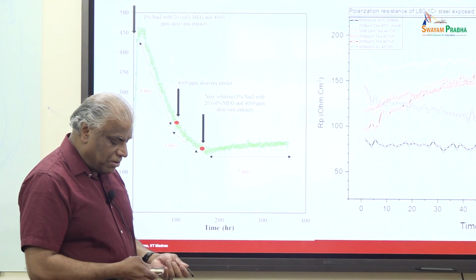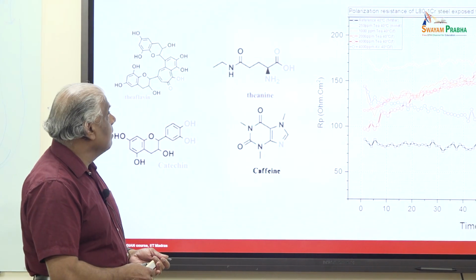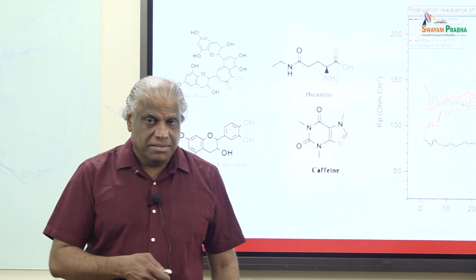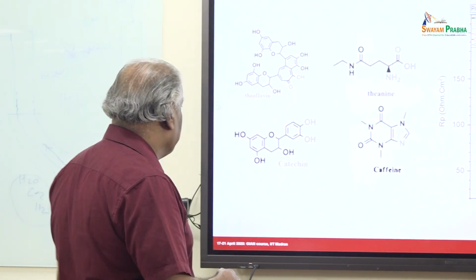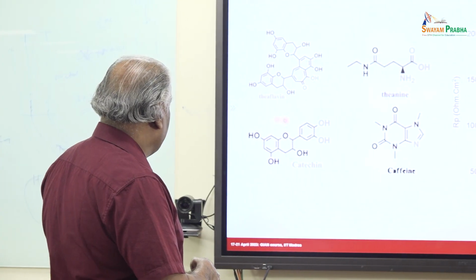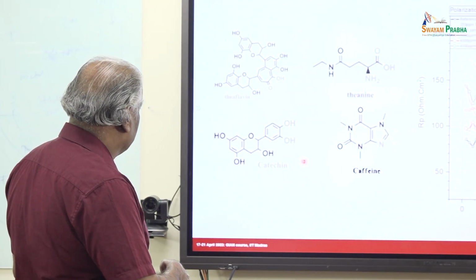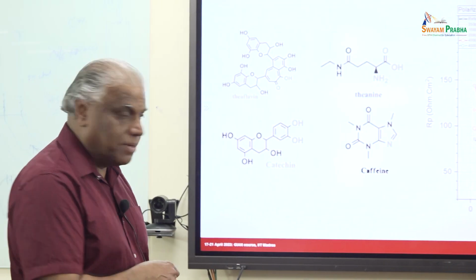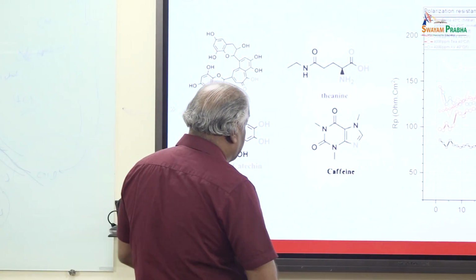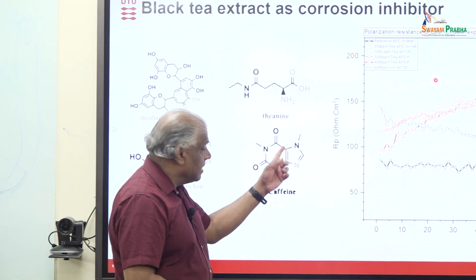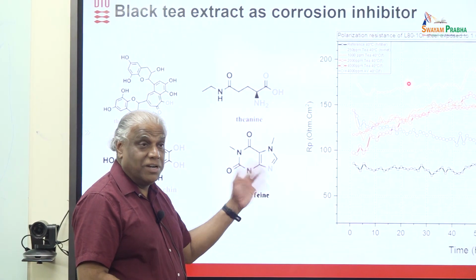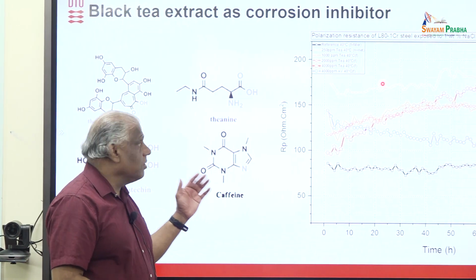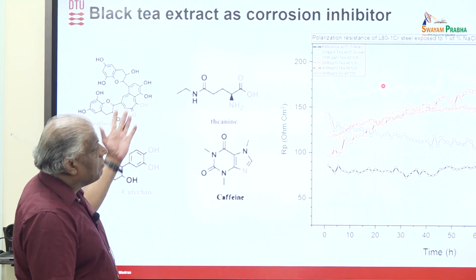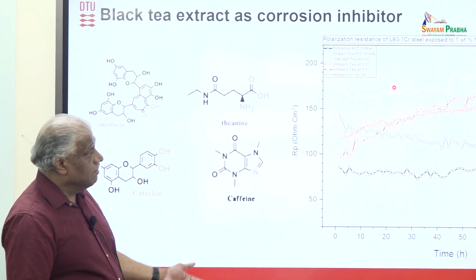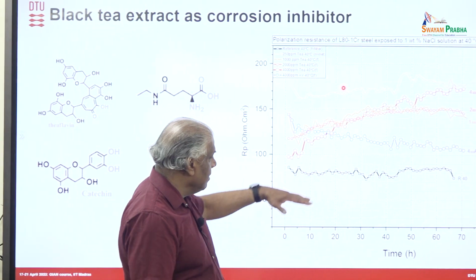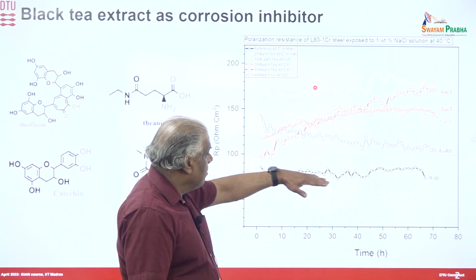That's the reason that now we also try another molecule, the black tea extract, which also contains many molecules like theanine and catechins. Caffeine as well. We thought that caffeine is a very good molecule for inhibition because of its nitrogen atoms, but we found that caffeine is the worst. It's not good from the inhibition point of view, but the black tea is probably better. You can see different levels of black tea compared to the reference.